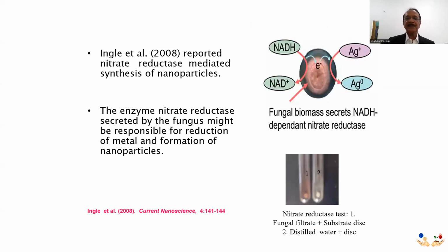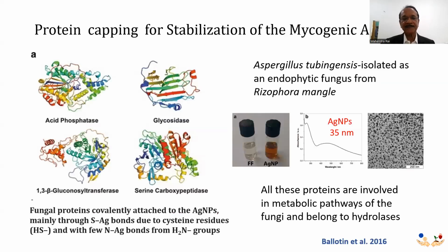We also tested the nitrate reductase enzyme. We treated the extract of the fungus with the disc of nitrate reductase, and we found that silver nanoparticles are formed. Whereas in the case of only the disc and distilled water, there was no silver nanoparticle; silver nanoparticles were not produced.